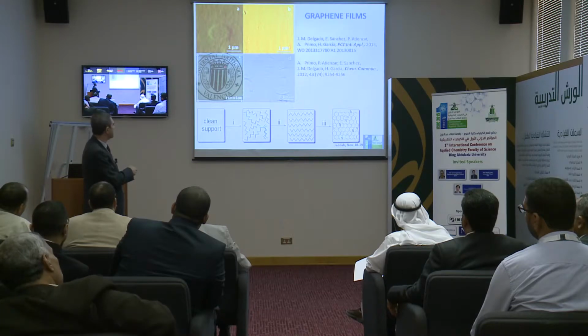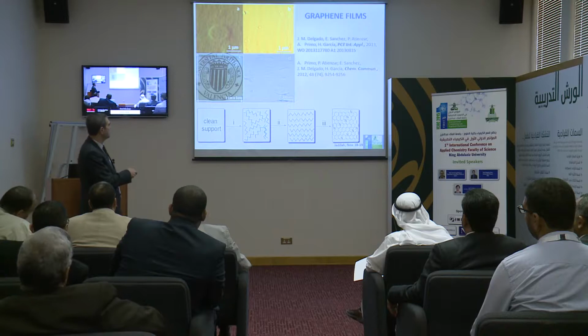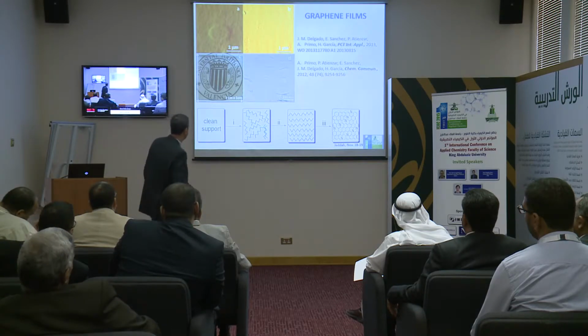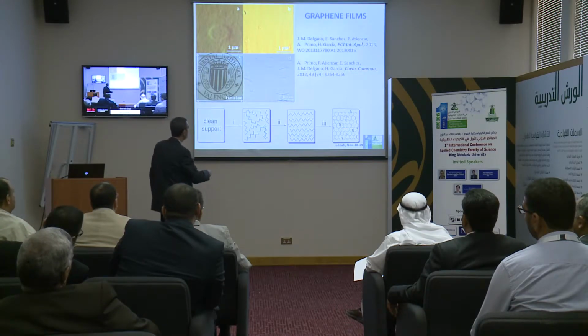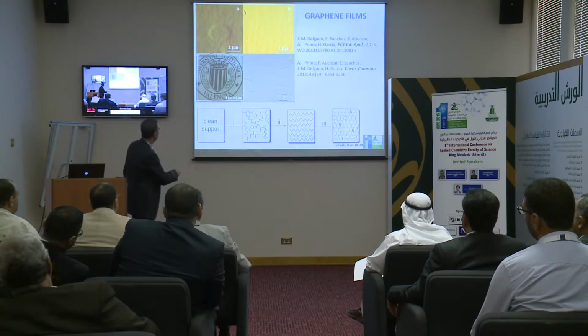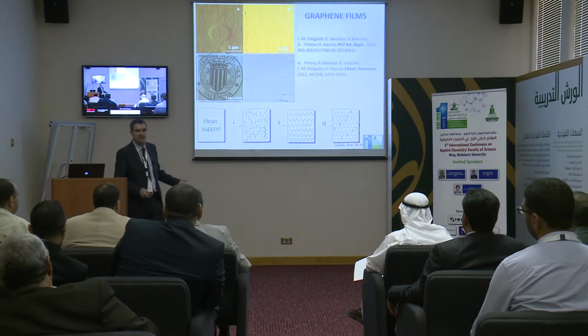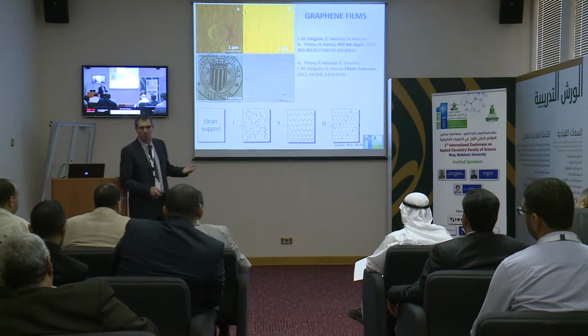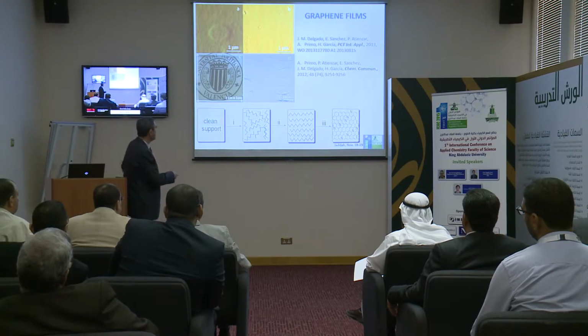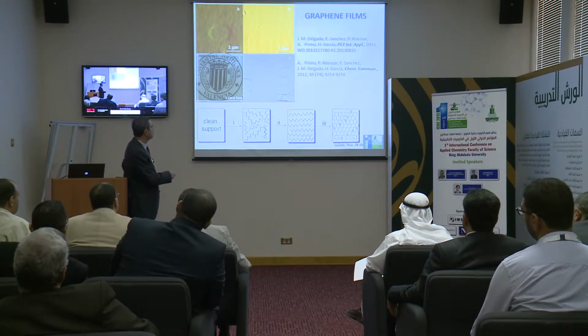And then we can scratch this graphene and go to electron microscopy, and then we observe here the presence of the graphene. So this is the process that we follow to prepare the films. The process starts with a substrate, typically quartz, but glass can also be used. And the glass has to be clean, and then we deposit the precursor, the biopolymer, by spin coating.